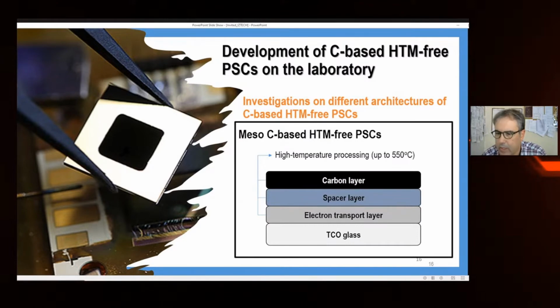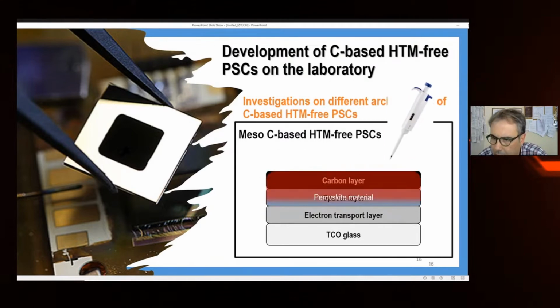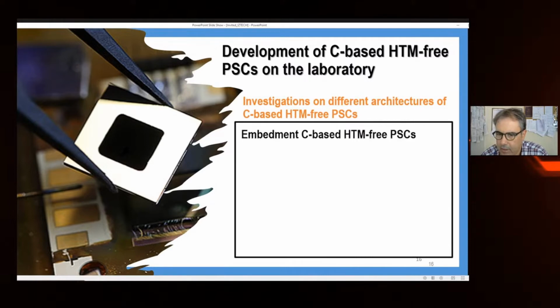To refer again, we bake the carbon at 550 degrees, which is really high for the needs of technology today, because the energy is very expensive, and to get ovens and bake the materials at 550 degrees is perhaps not a good option. After that we put in the perovskite with the infiltrated method, and we heat it a little bit just to crystallize it. And we have a perovskite, of course.